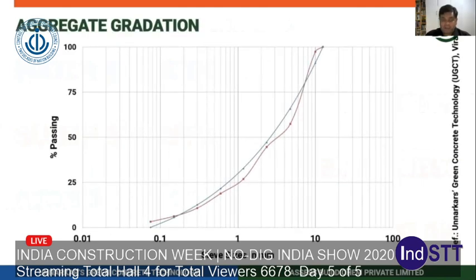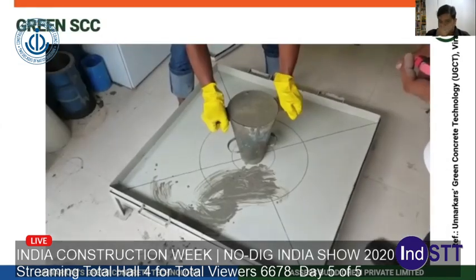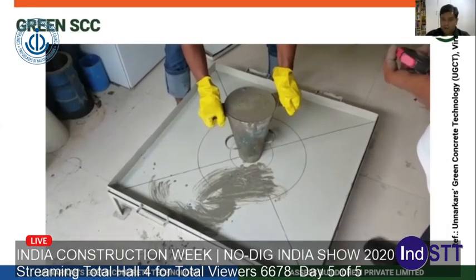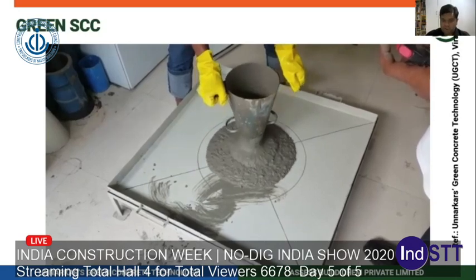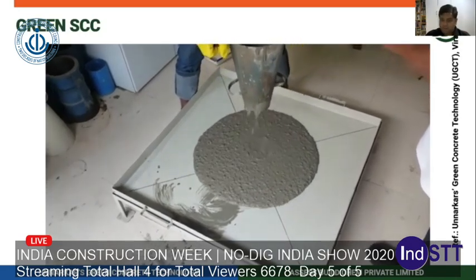So all these had to be taken care of, and that is what we did with the admixture. Of course, we created the aggregate skeleton using a maximum density curve. We went a little bit on the finer side so that the flow properties can be maintained. And yes, we were successful.